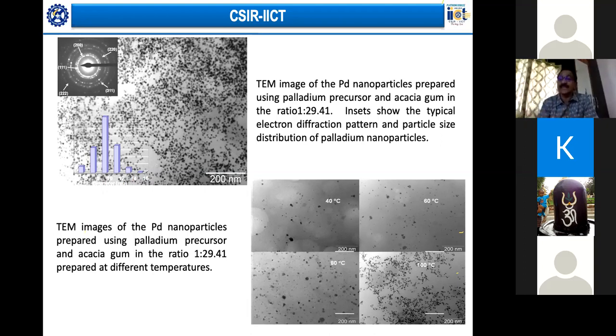So as I said, we have to do this at different temperatures because of optimization; the pH, temperature, and such things are all there. So we tried different temperatures like 40, 60, 80, and 100. You will see that at the lower temperatures, they are not so uniformly developed. It was only at 100 degrees that you start to see that there are plenty of them and their size is also uniform. So that is how we have to optimize the parameters.